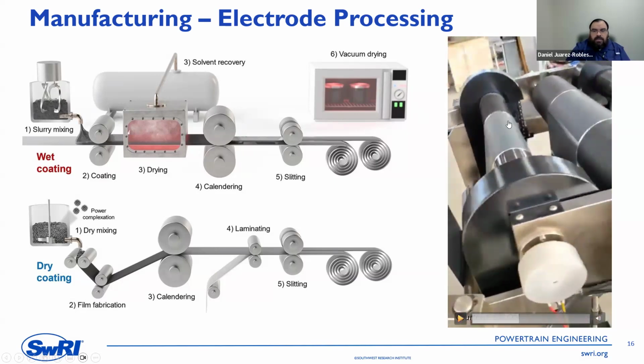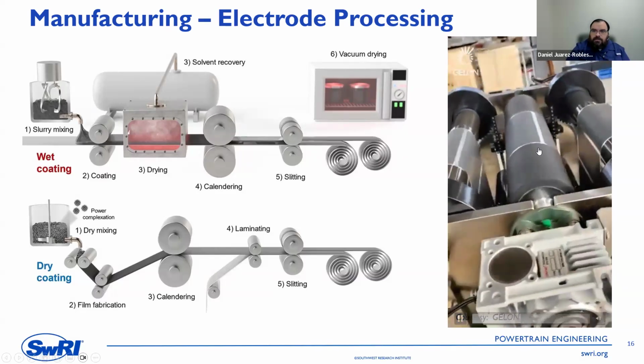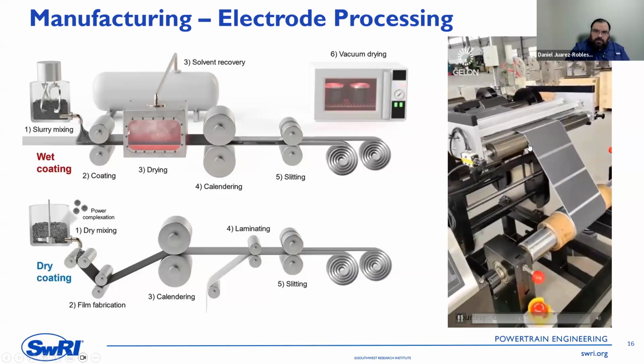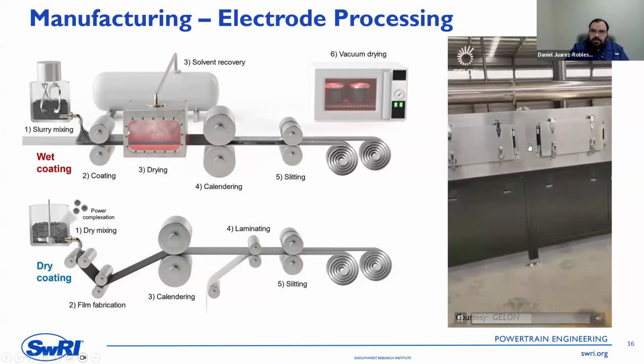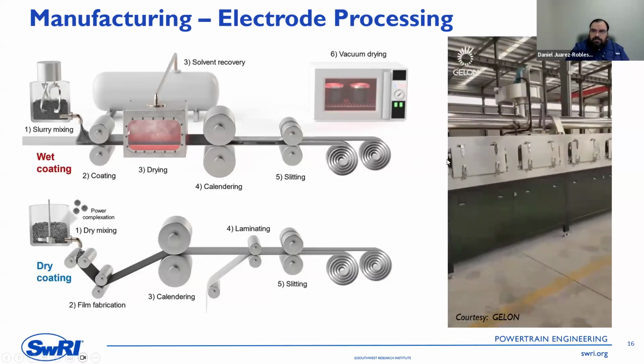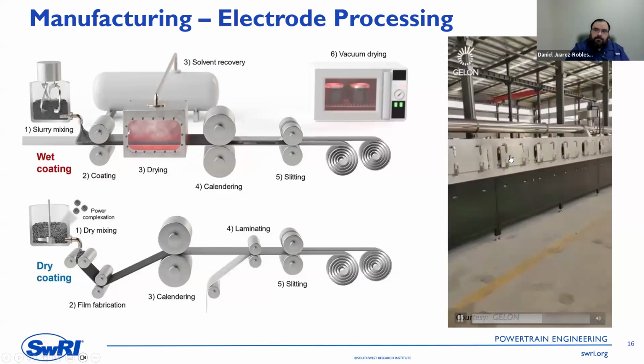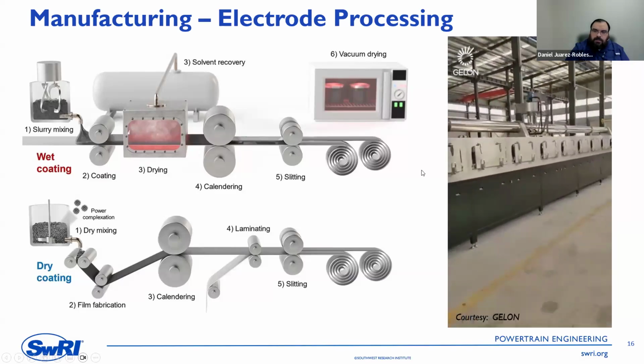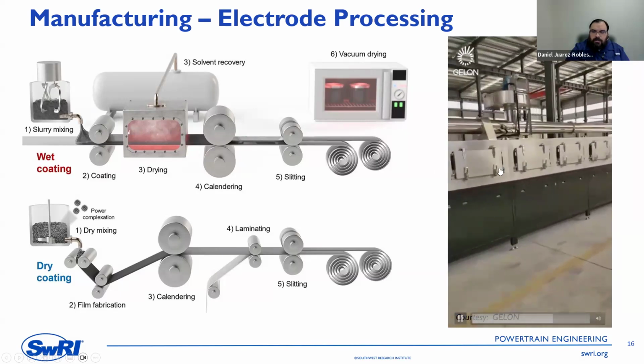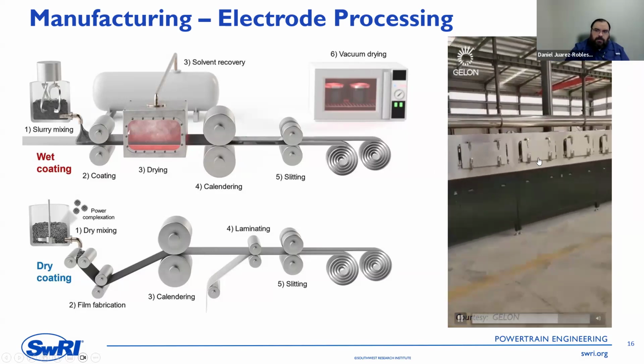Here, the electrode at the beginning was shiny, which means it was wet. It still had the solvent. Here you can see that now it's more dull, and it's because they already dried. The adhesion is really good. You can see that they are bending the electrode and still it's not detaching. This long line that you see here is where they dry the electrode. So the electrode is moving and it's drying, and they're controlling every single step.